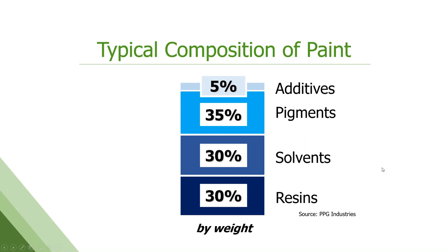This is the percentage breakdown of those components on average. Pretty evenly distributed between your resin, your solvent, and your pigment, and then a little bit of additives by weight at the end. And of course, all your solvents burn off in the curing process and are not on the final product. Our final product has no VOCs.